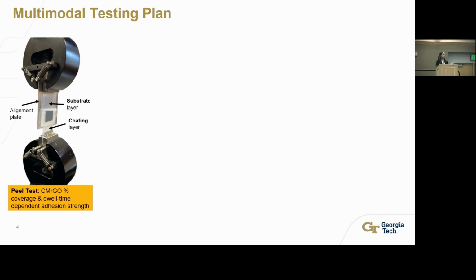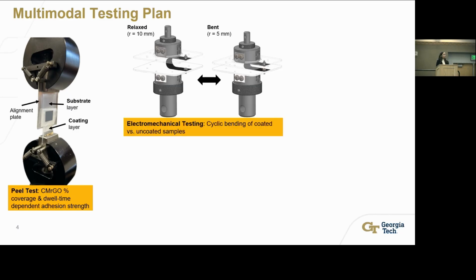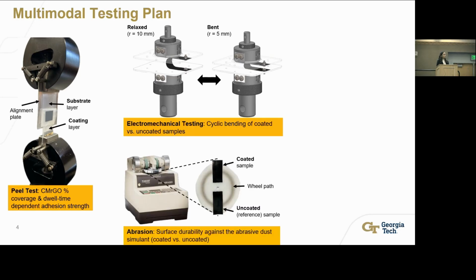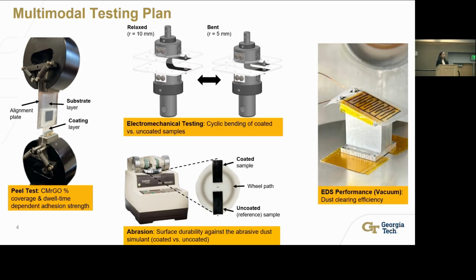Now, to test the performance of our devices, we have a multimodal testing plan involving a simple peel test to test and quantify the adhesion strength of our attachment. We have a standard compression test that is slightly modified so that we can cyclically bend our devices, but at the same time, we're also focusing on their sheet resistance measurements to track any changes to their conductivity. We have an abrasion test to see whether our coatings do indeed offer any sort of protection against the external stressors, which is the dust itself. And finally, an EDS performance test in high vacuum.